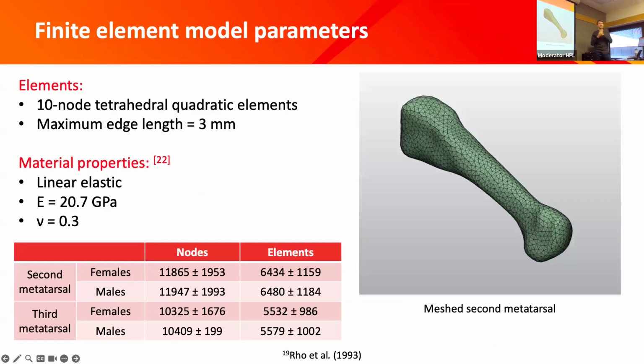All right, so now we have estimates of the force acting on the metatarsal heads. We have hopefully a pretty good estimate of the orientation of the metatarsal inside the shoe. Now we can make a finite element model of that to come up with the actual strains acting on the metatarsals. So we did this using 10-node tetrahedral quadratic elements with a maximum edge length of 3 millimeters. We used linear elastic material properties that we applied to all the elements within our model: a Young's modulus of 20.7 gigapascals and a Poisson's ratio of 0.3. And there's just some numbers there of the number of nodes and elements for the second and third metatarsal for the females and males. So the second metatarsal had about 12,000 nodes, 6,500 elements, and the third metatarsal was slightly smaller, so it had a little bit less.